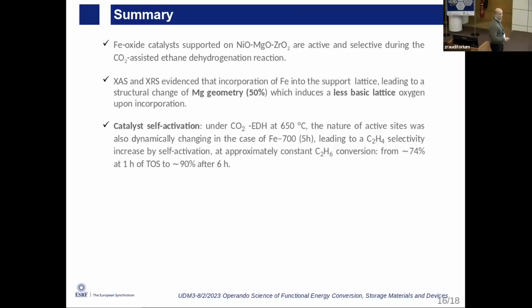So basically, we can sum up the results a bit. I don't know if I was too fast, but I think we need to go. So basically, we proved that iron oxide catalysts supported on nickel magnesium oxide, zirconia modified, are active and selective during the ethane dehydrogenation reaction. And X-ray absorption spectroscopy and X-ray Raman spectroscopy evidenced that incorporation of iron into the support is occurring, and in addition that magnesium in the fresh material at 700 degrees has 20% of magnesium in the tetrahedral coordination, and this becomes 50% in the used material, and the introduction of the magnesium in the structure induces a less basic oxygen upon incorporation.